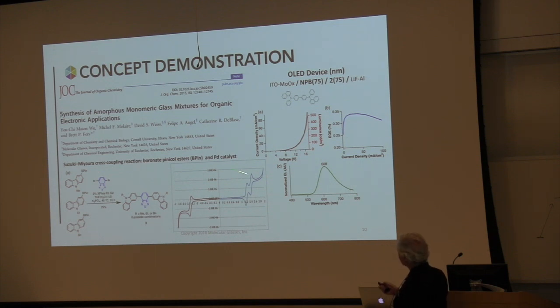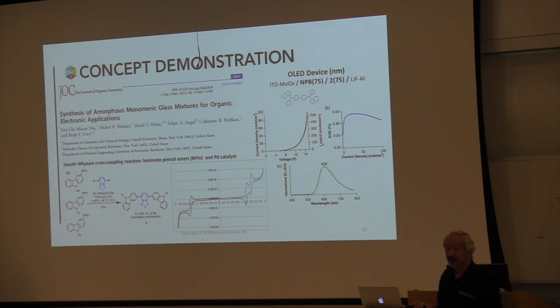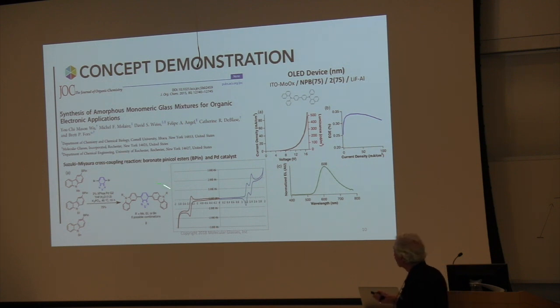If you look at the cyclic voltammetry in solution, what you see in the oxidation is two very clean oxidations, and then their subsequent reduction, very reversible. And if you go in the negative direction, you see a very clean reduction, and again, very nicely reversible. That's one of the things you have to have, right? If a molecule is unstable when you oxidize or reduce it, it won't work. So it has to be able to survive that. And these molecules are very, very stable to being oxidized and reduced. So we did this, and they said, well, it won't work.